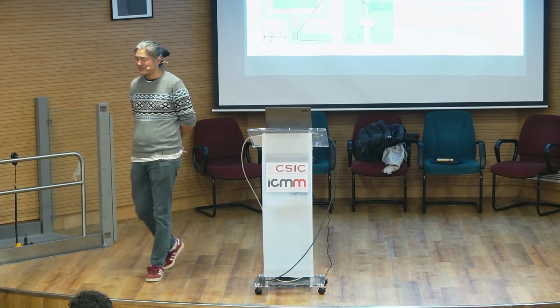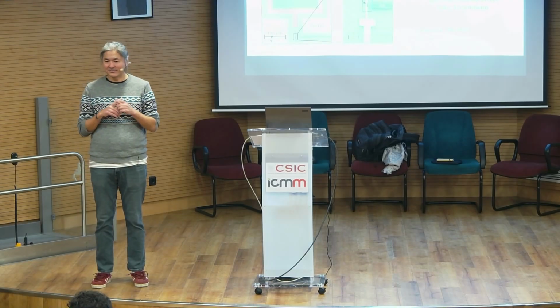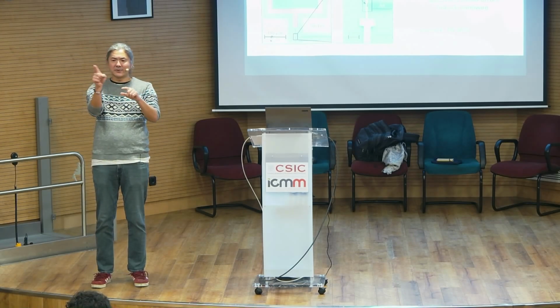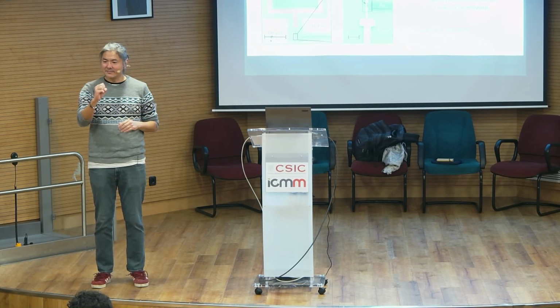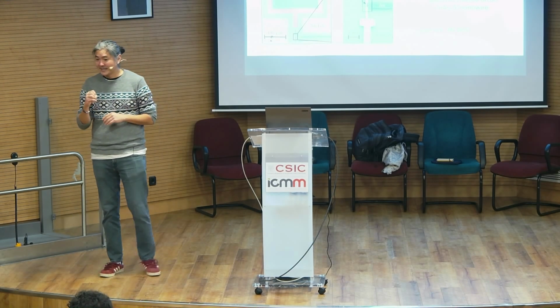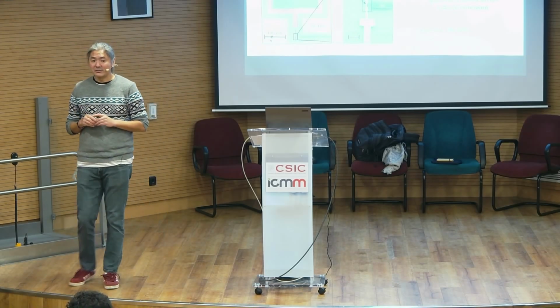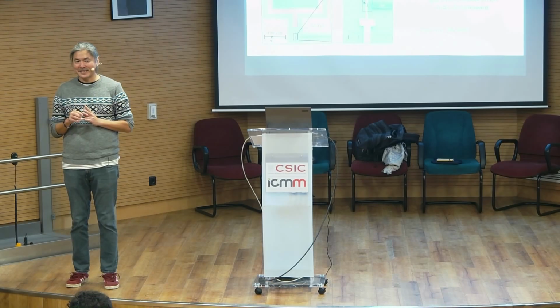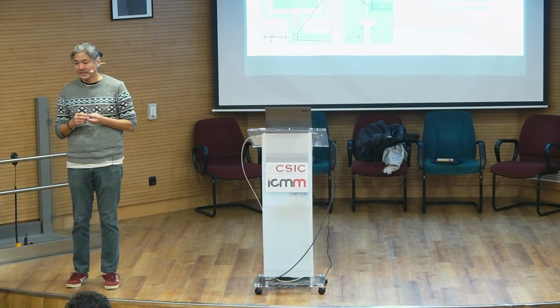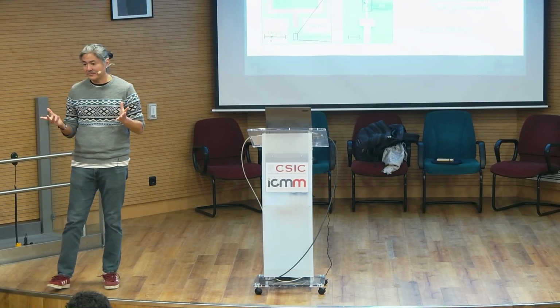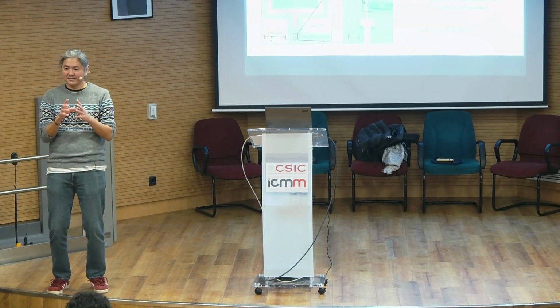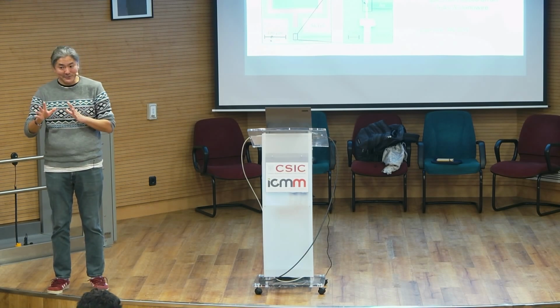We haven't really looked into this, because superconducting detectors, I'm not a specialist on this, but you have a grid or your pixel, right? You have a meander of the superconducting wire, where you have a sizable area that you can pick up this photon. I was also playing with a single nanowire at the beginning of the single photon detectors, because we were looking for a different perspective, not from photon detection. These wires have very small dimensions, lengthwise a few microns, and diameter-wise 100 nanometers or so. So I thought, it's very localized. We haven't looked at it from this perspective.